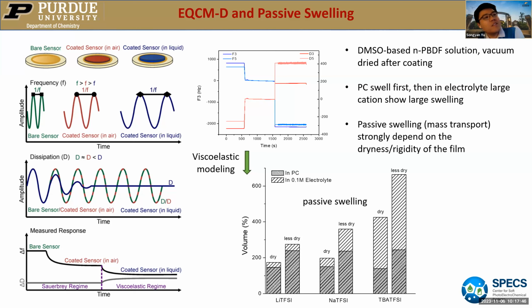One interesting behavior of this n-PBDF: we synthesize it into polymer in DMSO solvent. Then we coat this onto a substrate, then vacuum dry it. The interesting behavior is that the swelling or mass transport behavior strongly depends on how dry or how rigid the polymer is. If I do not dry the polymer enough, it will show higher swelling. And if I dry it completely, then it will have smaller swelling.